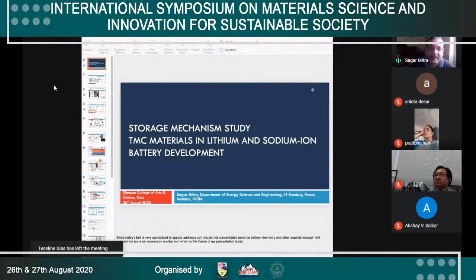Now the anode-free concept has come. If you think that this graphite is not there, and instead of graphite we have a current collector, which is copper, and you do the same charging process, lithium comes out from the cathode and deposits as a very thin film on the copper surface. On the next discharge, the same lithium can go out. This way we can make the battery anode free, and it is a concept that is going on right now.